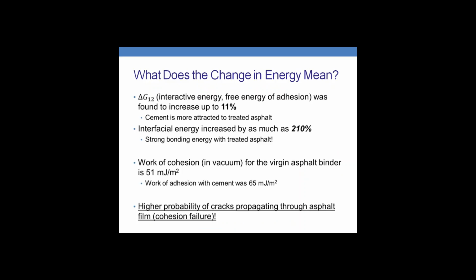So as you have a failure crack coming through here, it's going to go through the lowest energy state, which would be through cohesion rather than adhesion. So this is telling us that, great, we improved this energy of adhesion, but it doesn't matter because the cracks probably still just go through the asphalt as a cohesion, because it's a lower energy state.